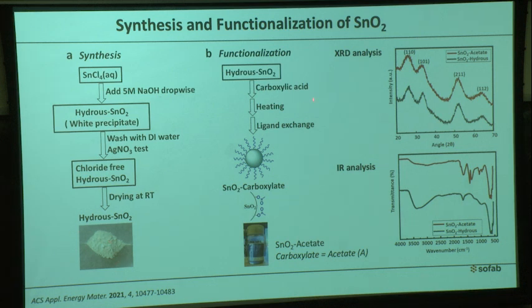I selected carboxylate as a proper group, mixed tin oxide with carboxylic acid, and heated it to high temperature. Whenever I heat it, finally I got a clear solution of tin oxide. This tin oxide contains carboxylic acid, carboxylate, attached on the tin oxide. That's why from powder we are able to get a clear solution.